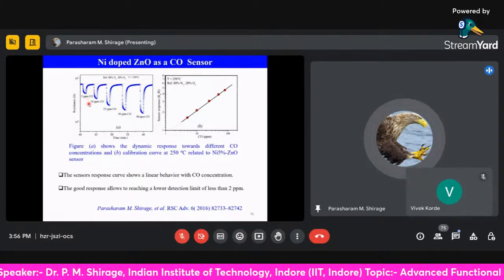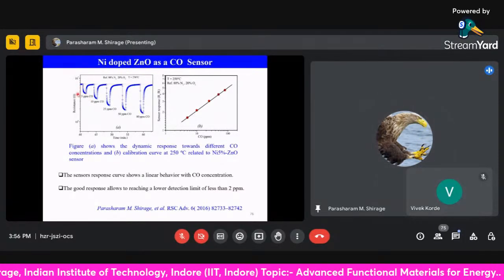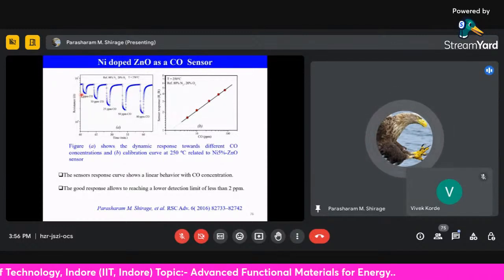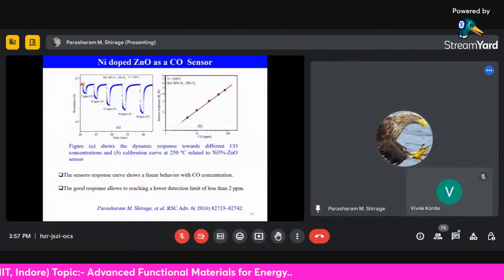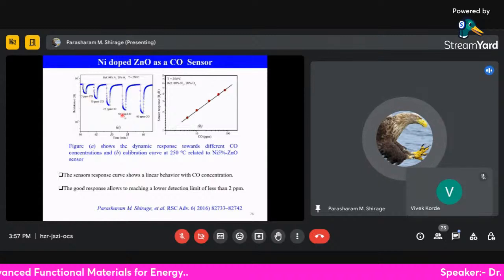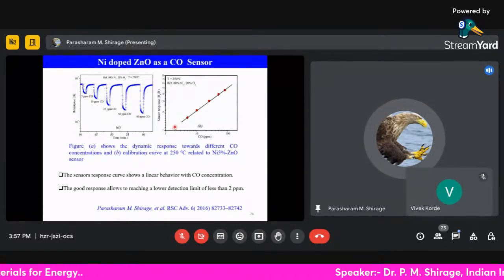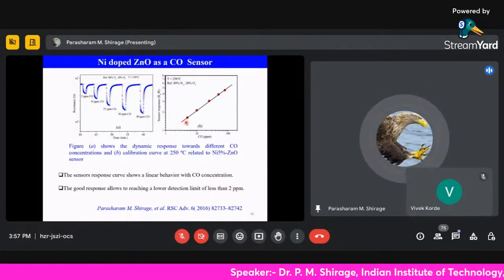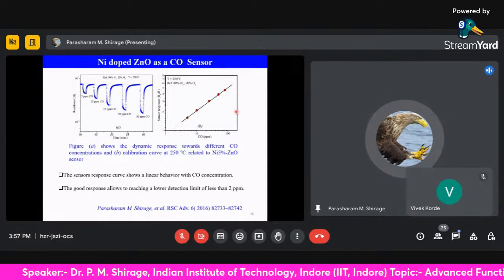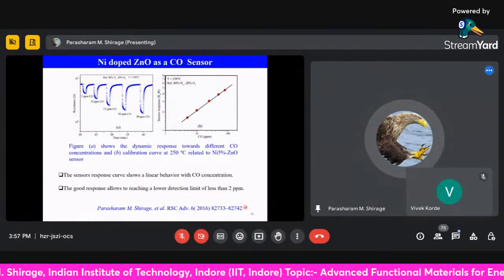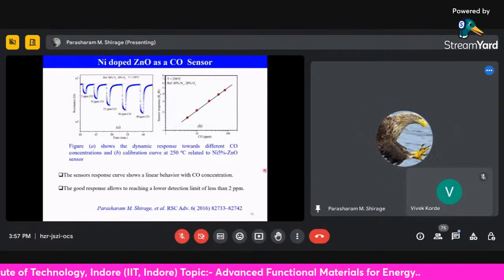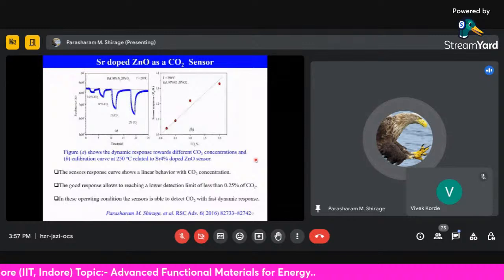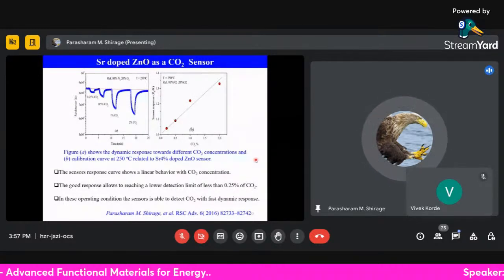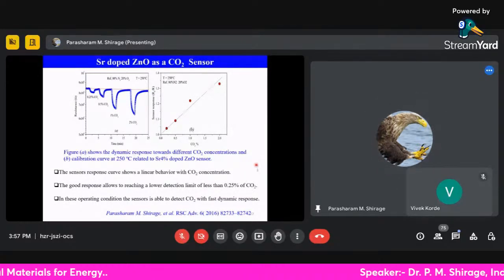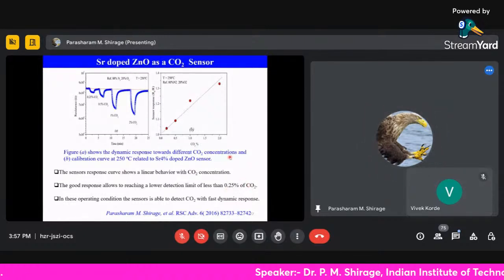Okay, so this response time and recovery time are very important, and this shows that on exposure to 5 parts per million or 80 parts per million, the change in resistance is systematic, and by using this we can calculate the calibration curve. By using this calibration curve, the minimum amount of CO that can be detected by this nickel doped zinc oxide sensor is about 2 parts per million. On the other hand, if we dope with strontium, this is good for the CO2 sensor, and it can detect down to less than 0.25% of the CO2. Okay, so this is also good.